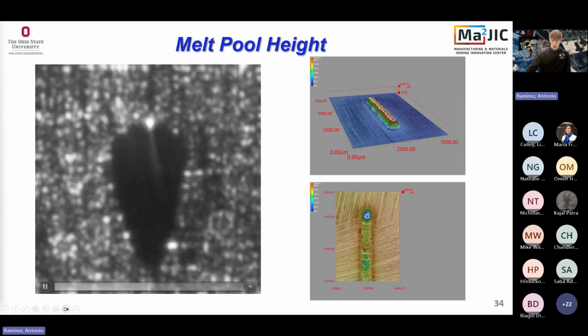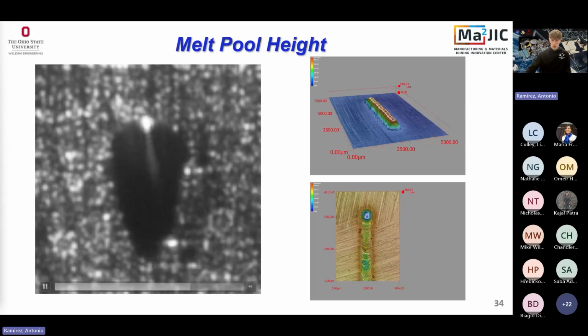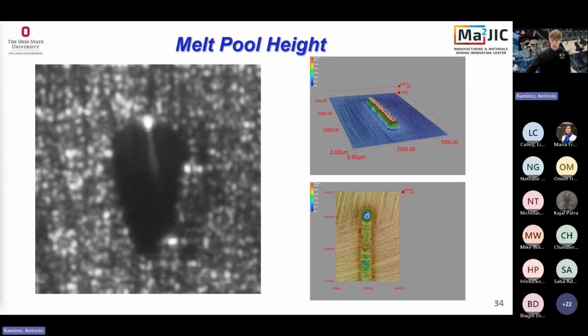Another thing that we find interesting about laser beam welding under microgravity is the height of the melt pool. You can see here, there's some shadow, but the melt pool is very, very tall compared to welds under regular terrestrial conditions. We did some optical analysis here, and the bead heights differ by something like 500 microns between welding under vacuum and welding terrestrially, which is really weird considering this is an autogenous process, which means there's no filler metal. So this raised bead here is very weird.